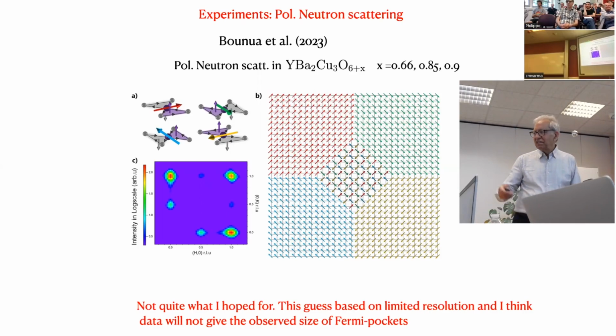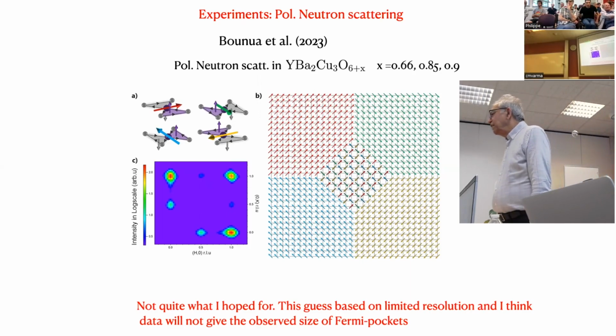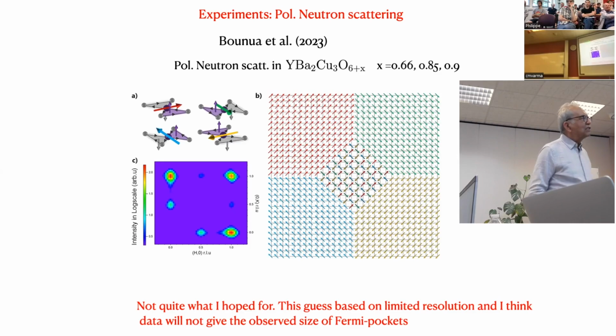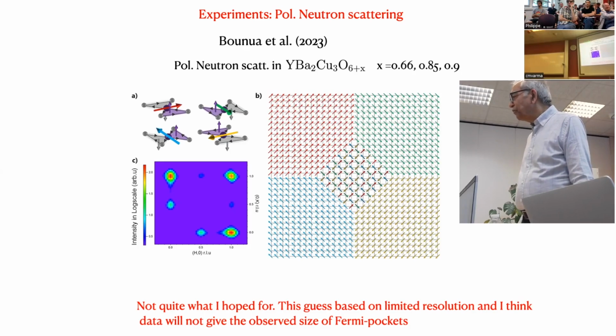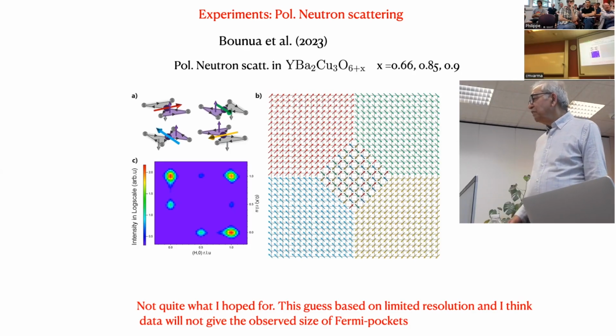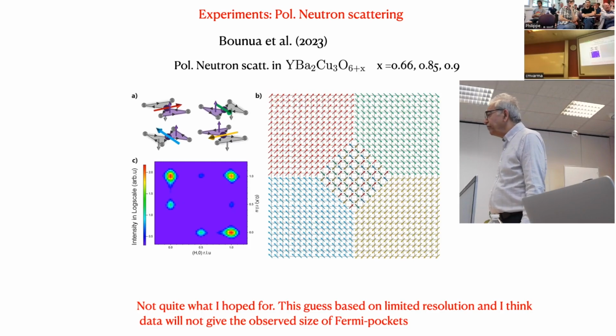And these had signals starting at specific temperatures, and what they find with neutron scattering, within the limited resolution that they can do it with, what we would have expected is that in this Brillouin zone there would be spots with decreasing intensity. What they found instead, within their resolution, was a spot here and here, (1/2, 0) and (0, 1/2), which is the pattern which I said should exist only at the corners, and so should hardly be visible if the domain is big enough.